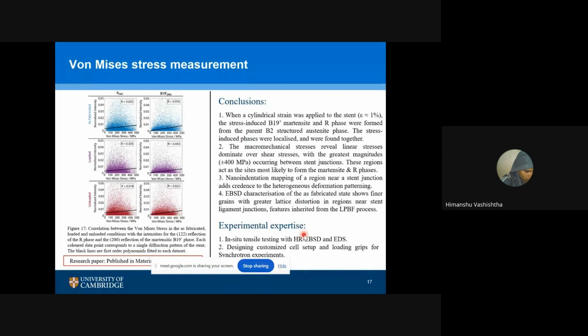Then we measured the von Mises component of the stress, and the R value, that means the fit index, which was pretty bad when as fabricated. That indicates there was no B19 or R phase there. When we loaded it, the fit index improved significantly, at least 10 times, so this R value goes down to 0.443.